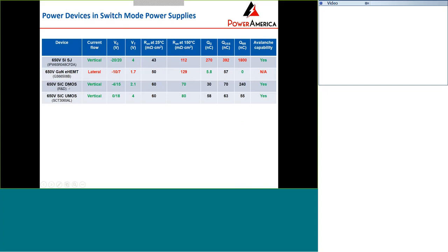All these devices have similar on-resistance at room temperature. But you can see that for silicon superjunction and gallium nitride E-HEMT, the resistance increases significantly at 150 degrees, while the DMOS and UMOSFET on silicon carbide increase only slightly at high temperature, as shown before. The advantage of the gallium nitride devices is a very small gate charge, and there is no reverse recovery charge. That is the advantage of gallium nitride compared to silicon superjunction or silicon carbide devices. The silicon and silicon carbide devices are vertical devices, and they have a higher threshold voltage or wider gate operation range, which are desirable parameters for the applications.